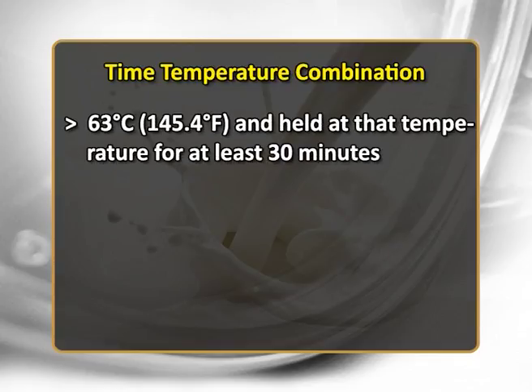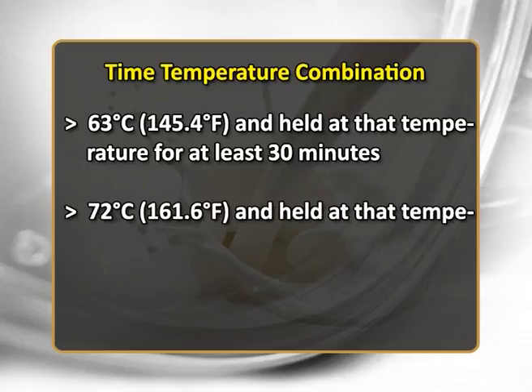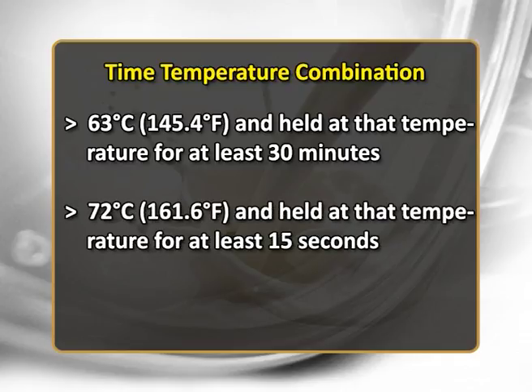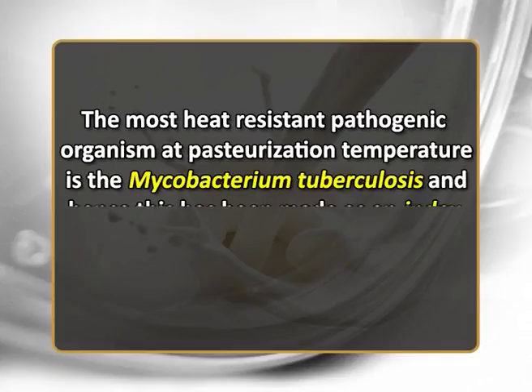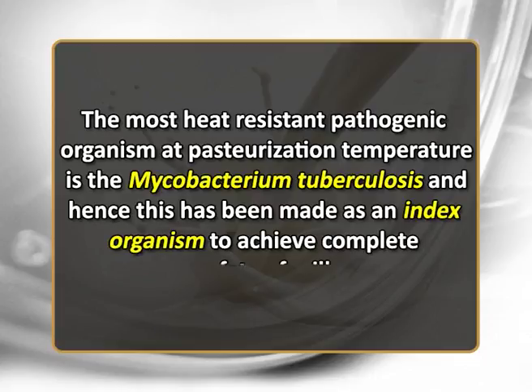Time temperature combinations: 63 degrees Celsius held at that temperature for at least 30 minutes, or 72 degrees Celsius held at that temperature for at least 15 seconds. The milk is then immediately cooled to a temperature not greater than 4 degrees Celsius. This means pasteurization includes heating to a specific time temperature combination followed by immediate cooling to 4 degrees Celsius. The most heat-resistant pathogenic organism at pasteurization temperature is Mycobacterium tuberculosis, and hence this has been made an index organism to achieve complete safety of milk.